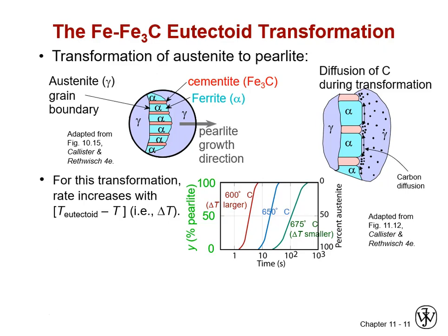Maybe you have someone waiting to do a follow-on process and want to know when it can be moved, for instance. There are quite a few diagrams and handbooks that you can use that have empirical data for given standard sizes based on heat transfer and transformation rates, where you can look this up. And this is an example of one type where you have time on the x-axis on a log scale and the increasing fraction of pearlite. This would be the remaining fraction of austenite.